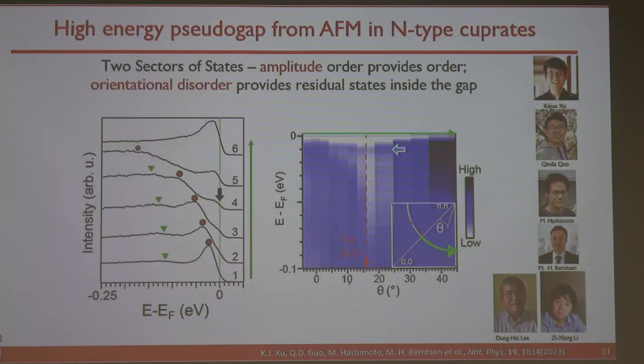Okay. But more recently, we were able to work with Donghai and Zhi-Xun Shen, based on more data, to show actually the physics is richer than that. Indeed, you see the spectra being suppressed at the so-called hotspot on the antiferromagnetic zone boundary. But the spectra show two components.